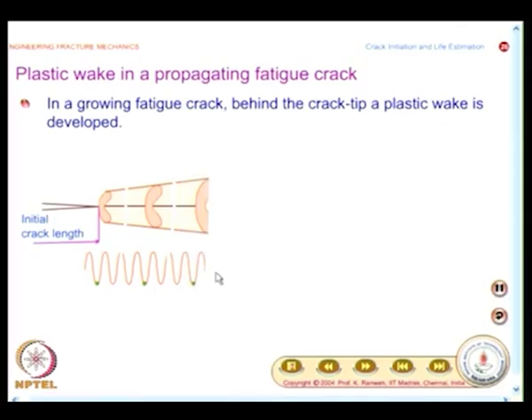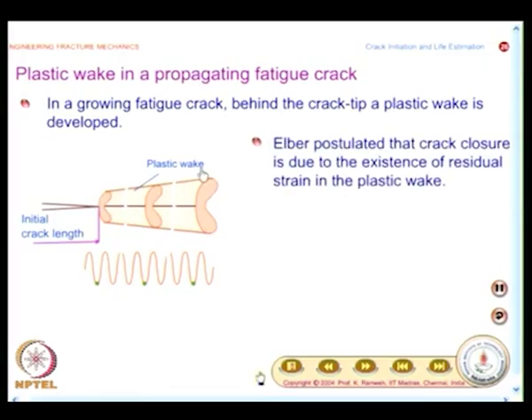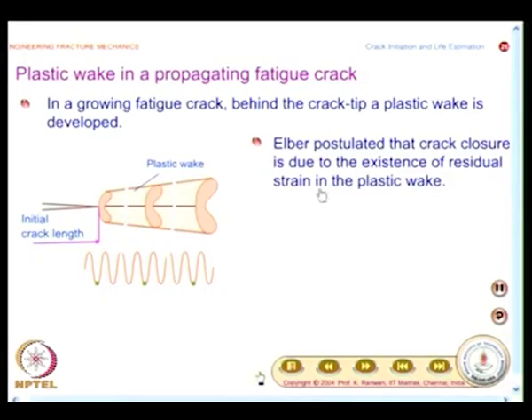That is what is depicted in the animation, and you observe it. It is done for sufficiently long distance, and the crack goes through plastically deformed portion, which is called a plastic wake. And what Elber postulated was that crack closure is due to the existence of residual strain in the plastic wake. See, if there is no fatigue loading, you will not have residual stress formation, because the load is increased and decreased, there is a residual stress formation. Because of the residual stress, the crack has to wade through that. Because of the existence of residual strain in the plastic wake, crack also closes.